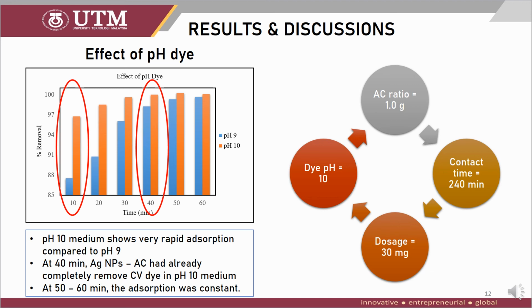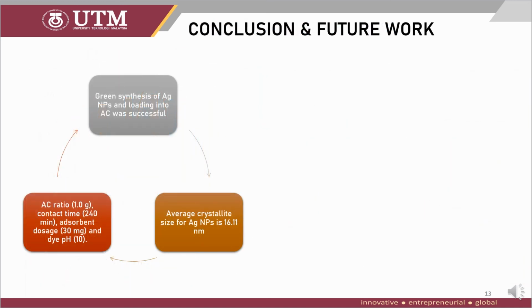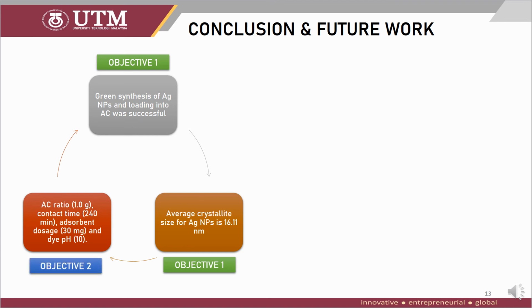So for the conclusion, this is the best parameter or the best condition in removing crystal violet dye using the AgNP-AC. The AC ratio is about 1 gram, the contact time is 240 minutes, the dosage is 30 mg and the dye pH is 10. So in conclusion, objective 1 was successfully conducted, which is the green synthesis of AgNPs and loading into activated carbon. And also, we know the average crystallite size for AgNPs is around 16.11 nanometer from the XRD analysis. And lastly, objective 2 was also successfully conducted, which is to analyze the adsorption capacity of the adsorbent in removing crystal violet dye. So this is the best parameter and the best condition in removing CV dye.